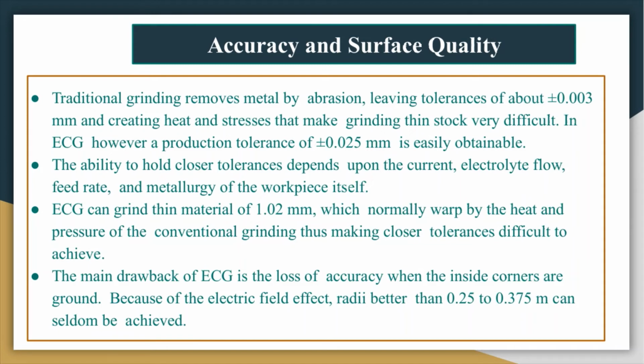When inside corners are ground, because of the electric field effect, radii of 0.25 to 0.375 mm can seldom be achieved. The reason for this problem is that the point of highest pressure of the electrolyte is at the wheel corner. However, high speed grinding benefits both inside and outside corners. The surface finish produced varies from 0.2 to 0.3 micron depending on the metal being machined, abrasive grit size, as well as the wheel speed and feed rate. For better surface quality, a finish pass at a low voltage of 3 to 5 volts and a relatively high speed of up to 250 to 500 mm per minute is recommended. This is again reported by one of the researchers.